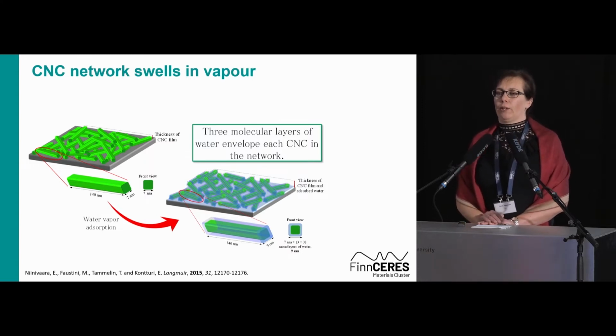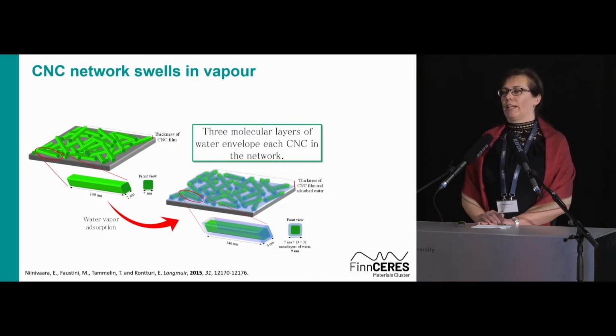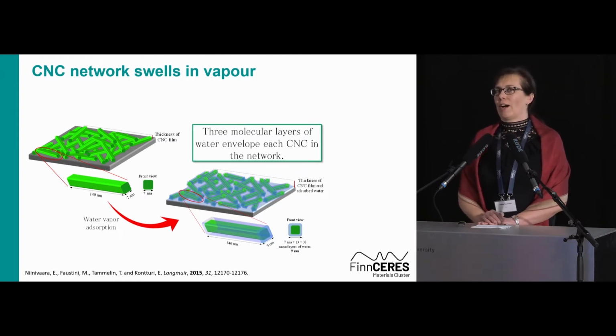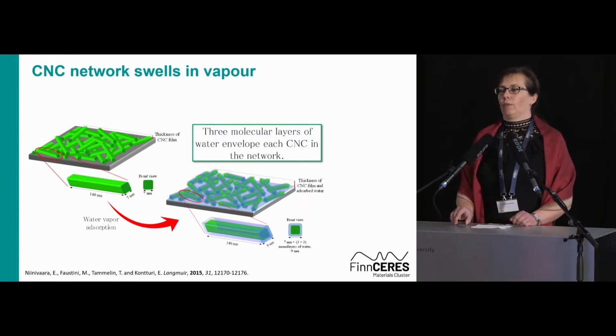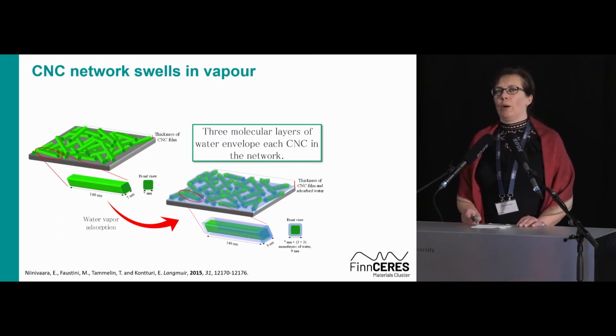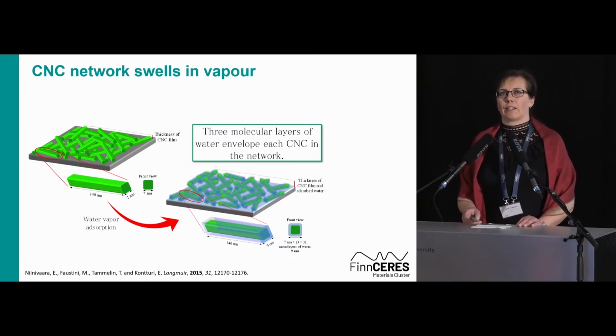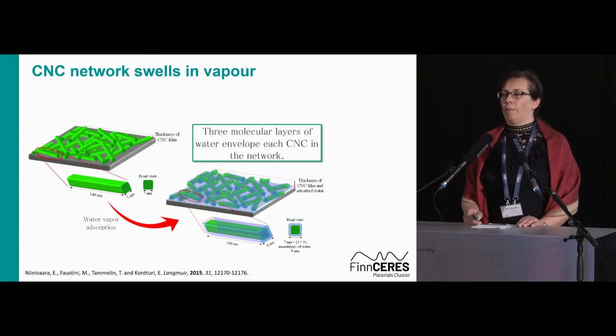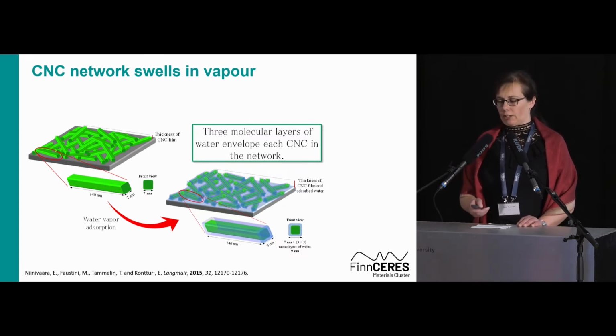And in the work of Elina Niinivaara, we were able to evidence that three molecular layers of water envelop each CNC in the network. And this means that there is a 1 nanometer layer thickness of water on the CNC layer. And I think that gives us an impression of the resolution and preciseness of this combination of surface-sensitive methods and ultra-thin films.